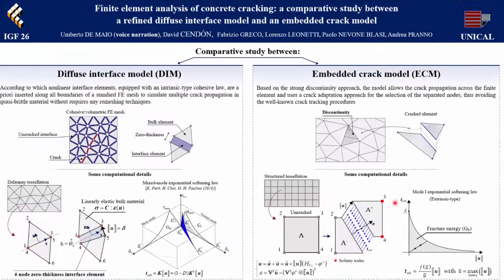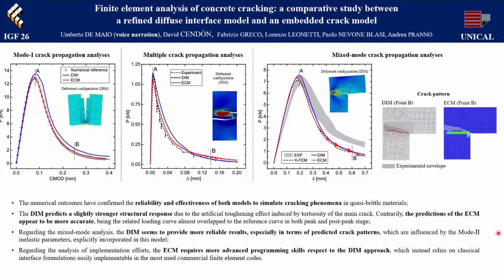Especially because you have this possibility to follow continuously this crack pattern, let's say. Concerning the computational effort of the analysis, the two models lead to a comparable efficiency, even if a detailed comparison in terms of analysis times is not conducted in the present work, since these models were implemented by using two different commercial finite element software.